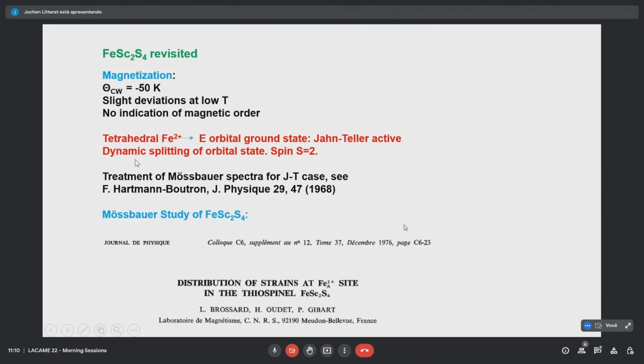From the crystalline electric field, we know, since we have tetrahedral iron 2+ in this case, that we have an orbital ground state of E-type, a doublet. And this is Jahn-Teller active, so we can have spontaneous splitting of that. Normally it will be dynamic. The spin is S=2, and the orbital momentum is also 2.